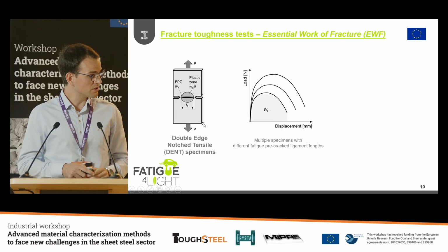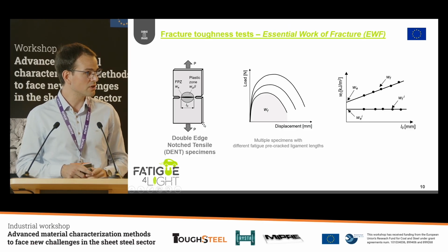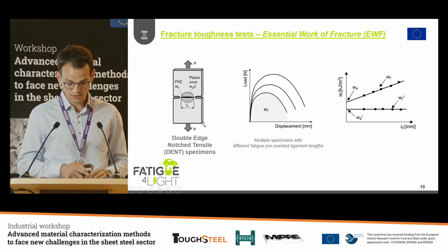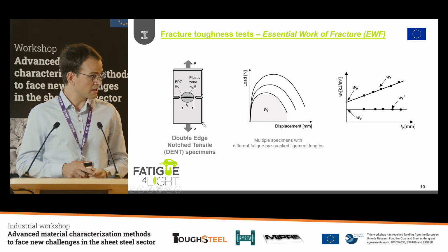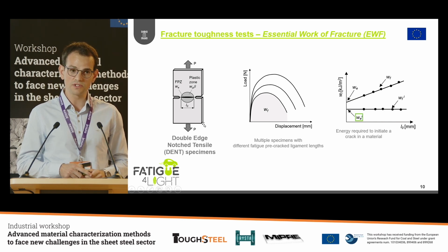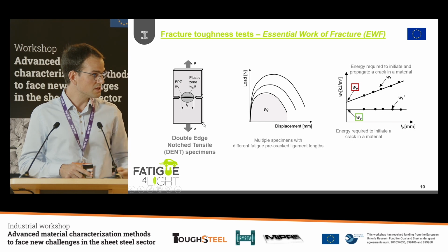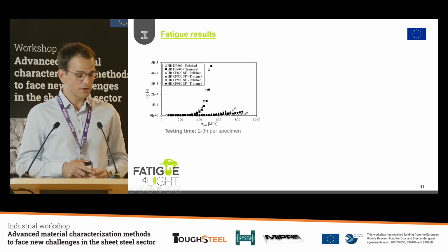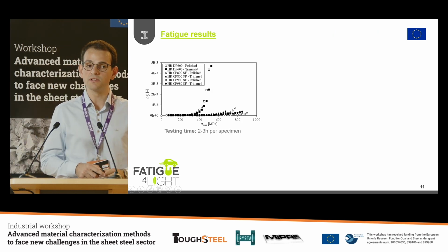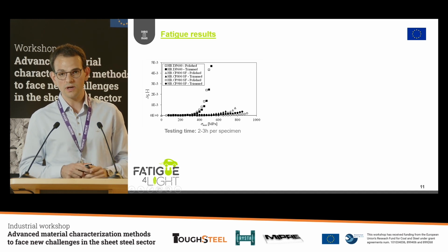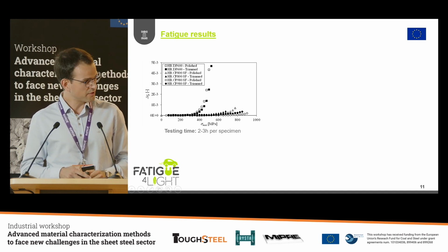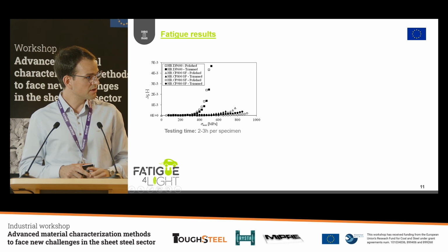So we also evaluated the fracture toughness by using the essential work of fracture. As has been explained, we can obtain the energy required to initiate the crack, but also the energy required to initiate and propagate this crack. And if we analyze the data that we obtain, the fatigue results from the rapid method, we can clearly see a difference.